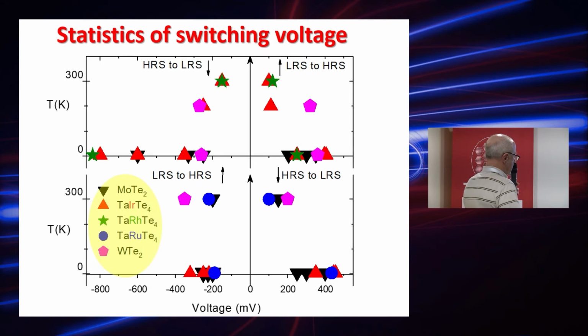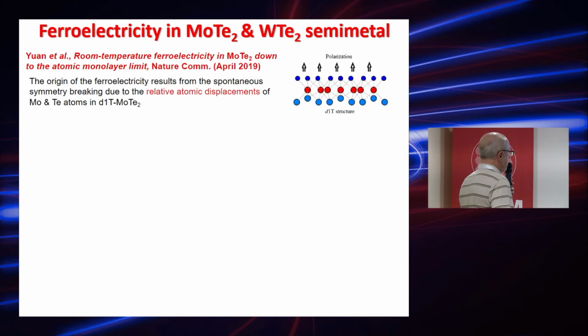So with increasing temperature, this switching voltage decreased. It was also observed that the amplitude of the effect also increased with temperature, but nevertheless, as I showed before, this change of resistance even at room temperature can be 2 orders of magnitude.